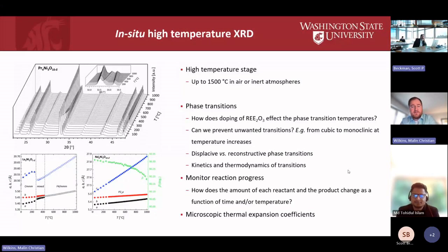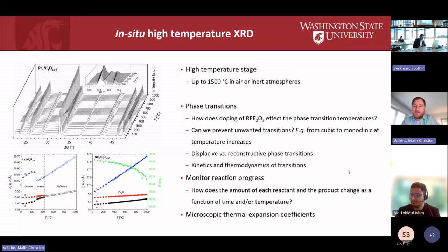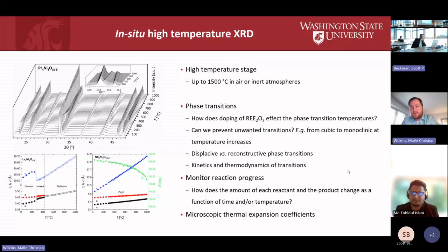You can also look at reaction progress as a function of time at a set temperature, or as a function of temperature at set times, as well as the thermal expansion coefficient. This is a microscopic thermal expansion coefficient — it doesn't account for grain boundaries or microstructure, but it still gives a good idea of how the material will change with temperature.